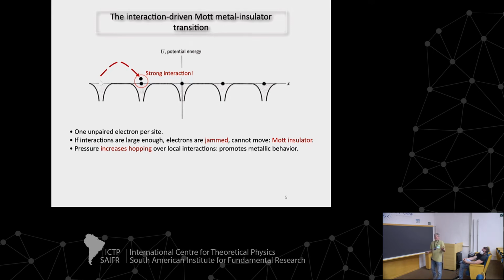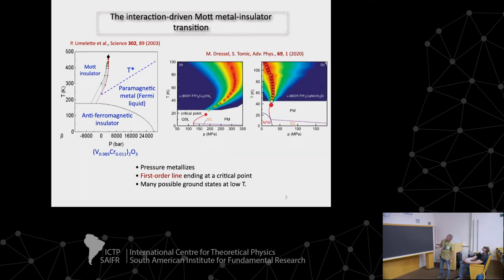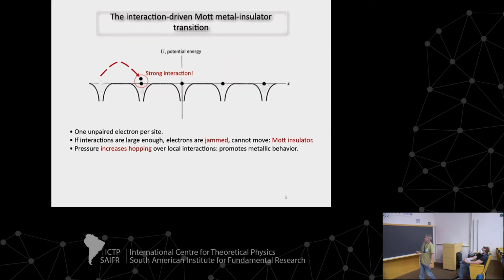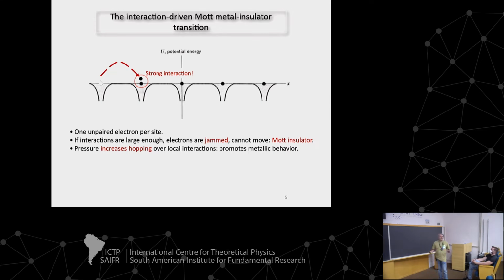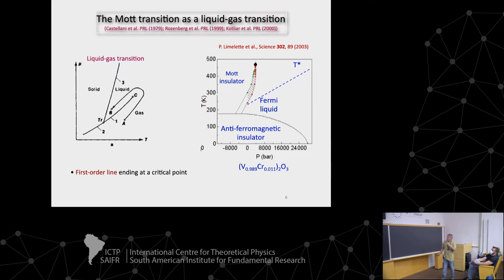And as we saw, if you apply pressure, I didn't emphasize it enough here, this is temperature versus pressure. So you see that whenever you put pressure in these systems, you go from the insulator to the metal. So what happens is, of course, that pressure increases the hopping and effectively decreases the interactions relative to the hopping, and then you can metallize the system and have a metallic phase. So that's the basic physics.